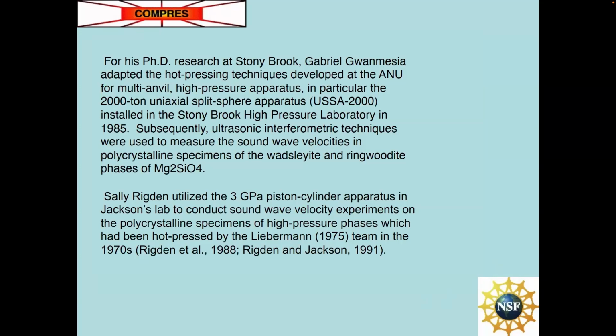So one of the things we needed to do, we have a technique to measure the sound velocities, but we needed some specimens. And as part of his PhD research, Gabriel Gwanmesia developed and adapted some of the hot pressing techniques that Ringwood had taught me in Australia to be used in our high pressure apparatus at Stony Brook. And then those hot pressed polycrystalline specimens were used by ultrasonic interferometry to measure the sound velocities, in his case, for his thesis in the high pressure forms of forsterite, Wadsleyite, and ringwoodite.